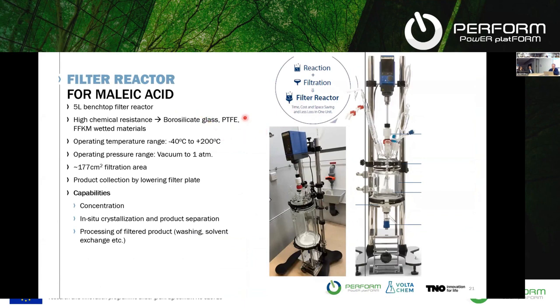We have this new filter reactor where we can carry out different procedures within the same setup. In general, after the pre-concentration with the nanofiltration, we can put this concentrated solution in here, and we have the freedom, for example, to increase the temperature and apply vacuum to remove even a bit more water, so concentrate a bit more, or we can lower the temperature with a jacketed vessel.